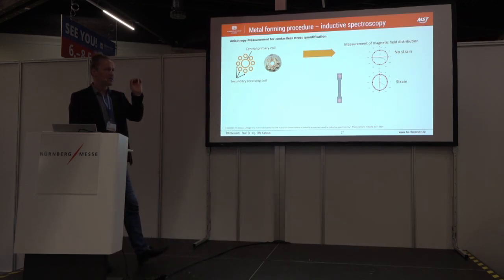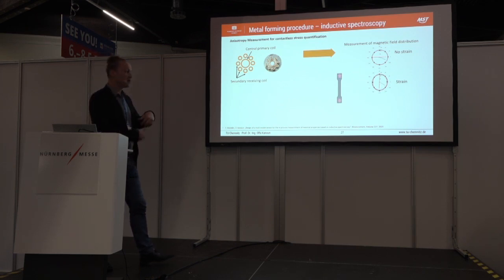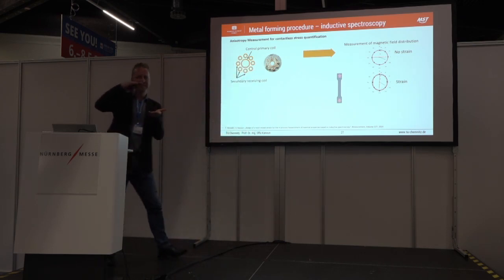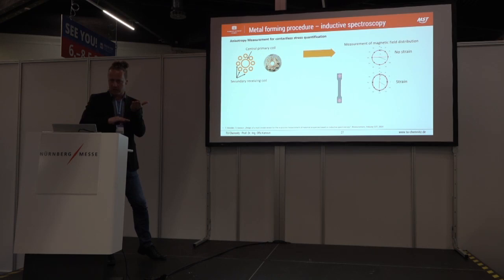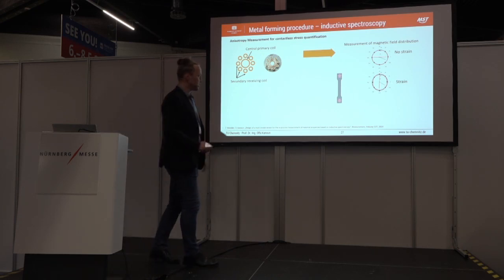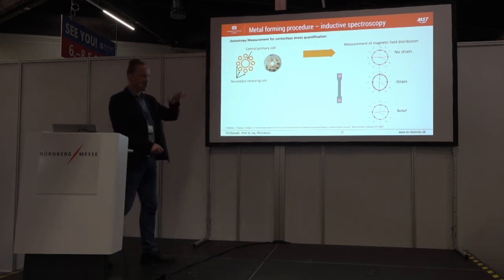And to make the story short, we can detect changes in the permeability of the material. And all aspects which cause a change of the permeability, we can detect. And this is, for example, strain, temperature, also the grain growing. If you make hardness, for example, you have bigger grains causing a change in the permeability. We can measure with our sensors the depth of a hardening procedure, for example, without destroying it. And also the relief, the surface, we can observe.